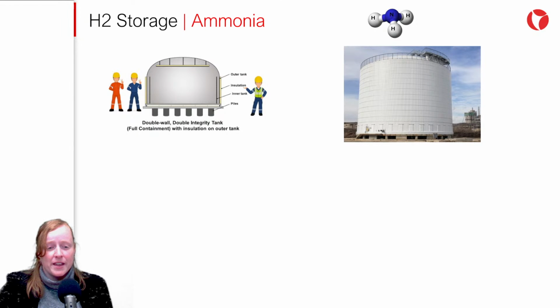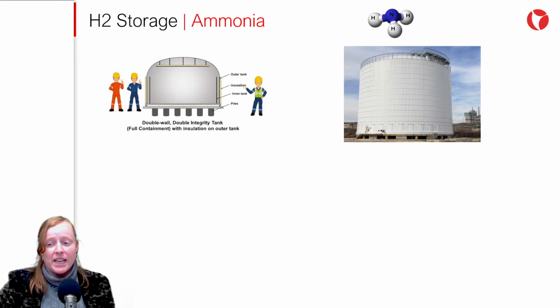Another common construction method is the use of a double tank with insulation in the annular space. This option is more economical, but would require decommissioning the tank in case of an internal tank failure. In double-wall designs, the inner tank is designed to contain the entire nominal volume. Both tanks are made of the same material, normalized carbon manganese steel. The support pylons under the tank are usually made of treated wood. These are preferable to concrete blocks at the bottom of the tank for insulation reasons.